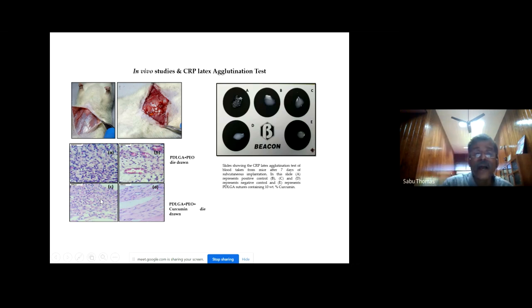We also did the C-reactive protein (CRP) test, the latex test. You will find that the first one is actually the positive control. You can see that a lot of information. And B, C, D are negative controls, okay? And this is our sample. You see, our sample with the PU and curcumin with the biocompatible polymer showed excellent results.